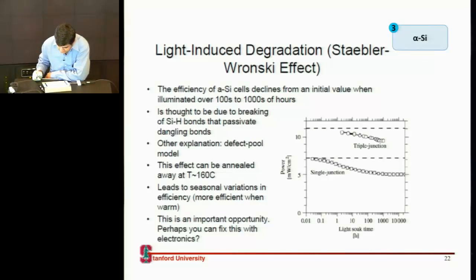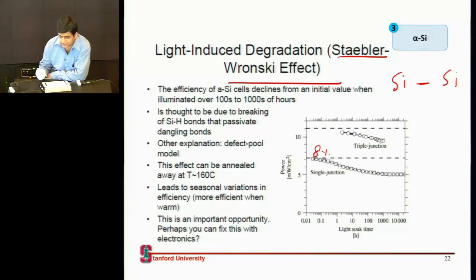Where was I? So now suppose you have even made these cells and you have demonstrated, let's say, efficiencies of 8% in single junction. Now as soon as you place these cells in sunlight, the efficiency starts to degrade, and that has been well known in these amorphous materials all the way back in the 70s and 80s. And the reason why this happens is that the bonds in an amorphous material, the silicon-silicon bonds, are weak, right? So when you shine a lot of light on these materials, it would generate these electron and hole pairs.